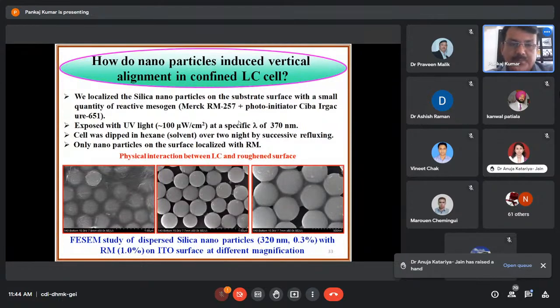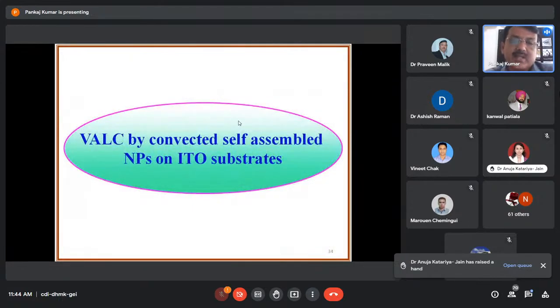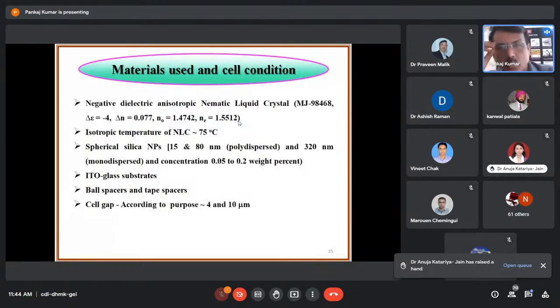pure cell. Now the second approach which we have used, that is the VALC by convectively assembled nanoparticles on ITO substrate. So in the first approach we have used the doping of the nanoparticles. However, in this approach we have coated the nanoparticles on the substrate surface. So negative dielectric anisotropy nematic liquid crystal again we have used, and you can see here the dielectric anisotropy as well as the other characteristics.